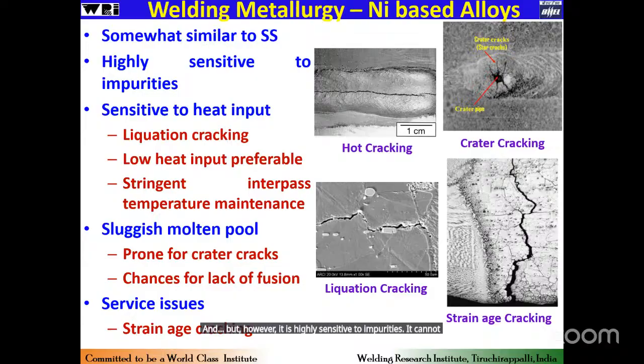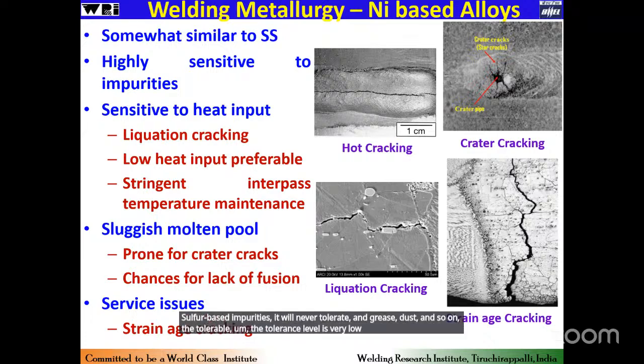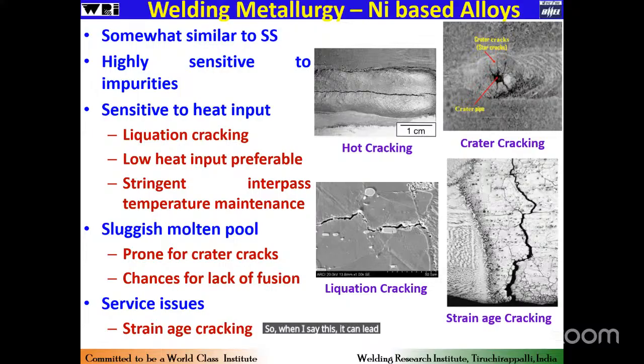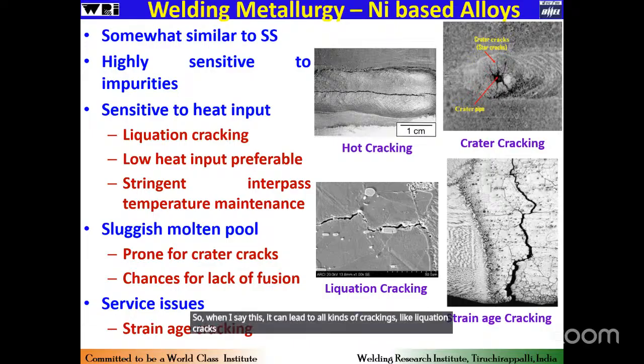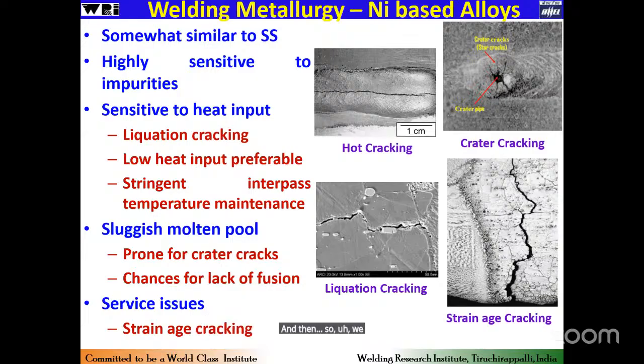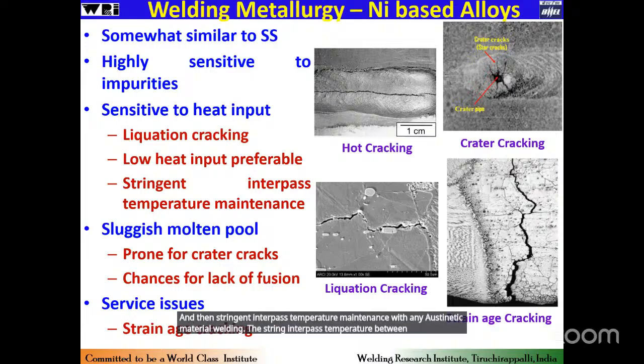It cannot tolerate impurities, especially the sulfur-based impurities. It will never tolerate grease, dust, and so on. The tolerance level is very low, and it is highly sensitive to heat input. So when I say this, it can lead to all kinds of cracking, like liquation cracks, which are usually seen in any austenitic grade of materials. And then we have to go for lower heat input based processes, and stringent interpass temperature maintenance with any austenitic material welding. The interpass temperature between the two passes has to be controlled and maintained throughout.